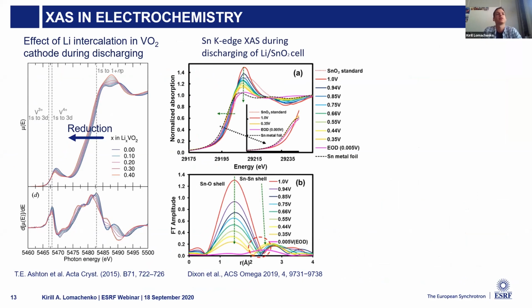In these 2 examples, you see that it's possible to follow the discharge of the battery, for example, and the evolution of the local environment of particular atomic species in the cathode or anode of the battery, like vanadium in the case on the left and tin in the case on the right.